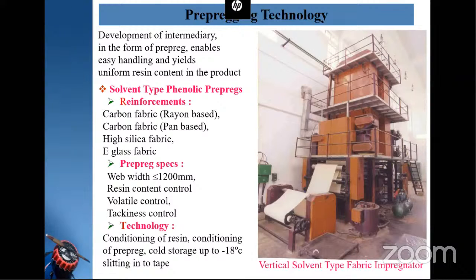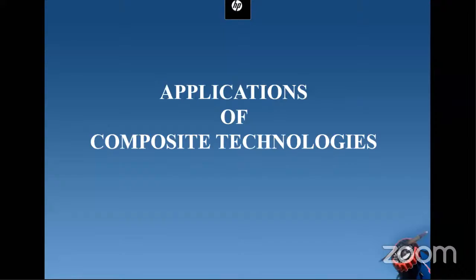Here we are making different varieties of fabrics like carbon fabric, rayon-based carbon fabric, PAN-based, high silica fabric, and E-glass fabric. Normally the fabric comes in a width of 1.2 meters. In this impregnation process, we have to control the resin content, volatile content, and tackiness. For this, we have different parameters like squeezing, then heating, then cooling. All these parameters we have to control while doing the impregnation process.